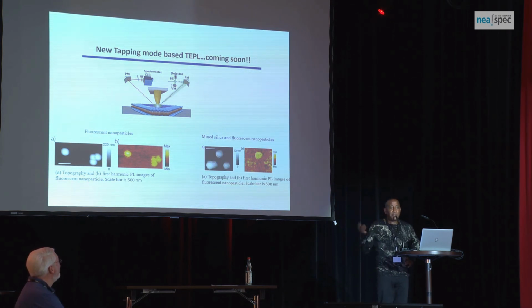This is the coolest thing I should have been talking about, but we are now trying to do with NeaSCOPE. That's the beauty of working with NeaSCOPE, they're more like collaborators to me, and they're open to new ideas. And so we're trying to do this with tapping mode AFM as opposed to simply doing hyperspectral with a CCD. Can you do a similar thing you do with a regular scattering-type SNOM for inelastic scattering by using tapping mode? This is the first data. We have had this data for a couple of years now. We haven't written anything yet, but it has the potential that it is possible. It's not as sensitive as elastic scattering, but we did initial measurements.